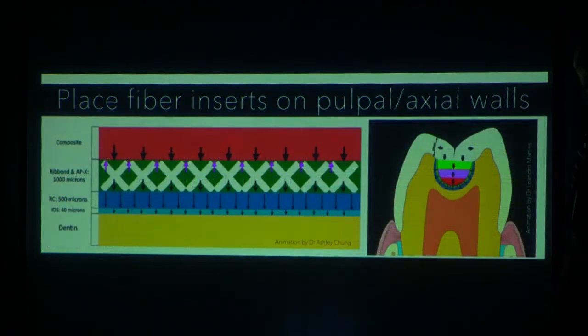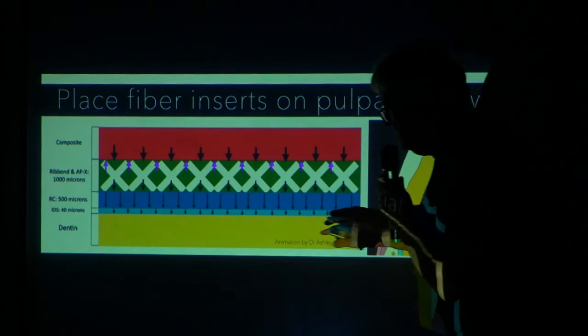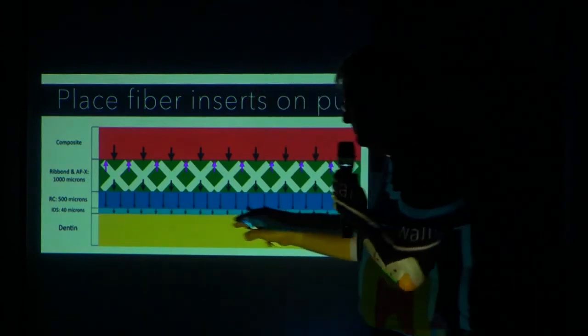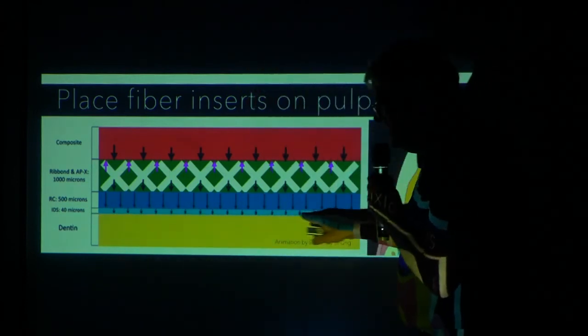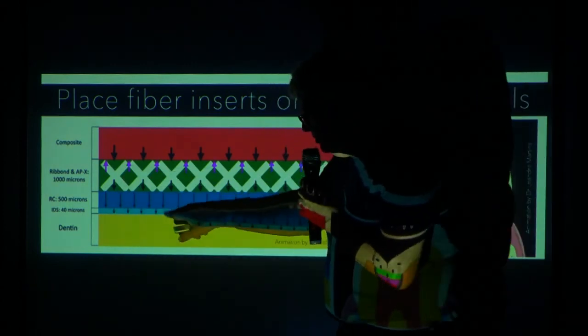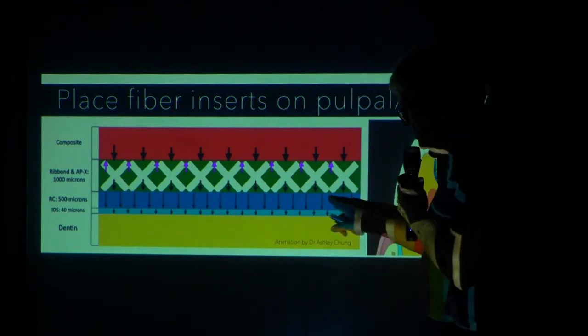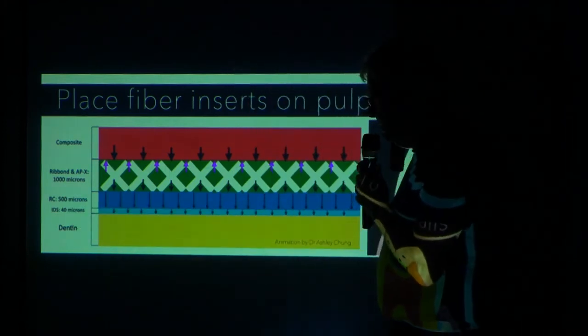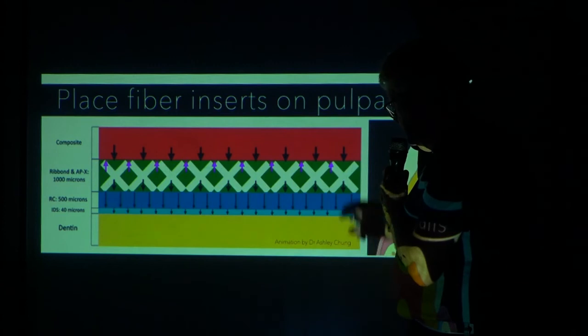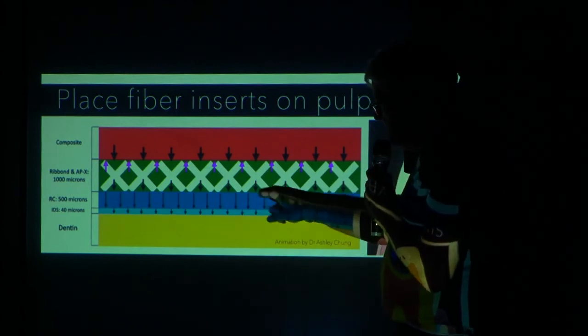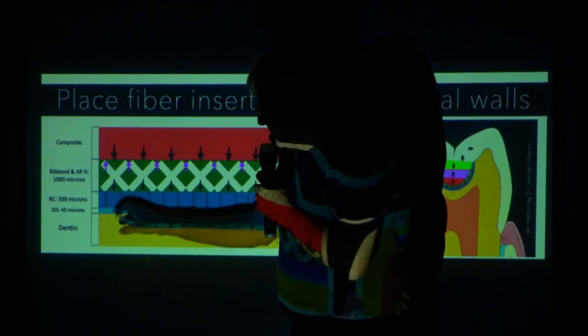So this is how Ribbond works. We have a hybrid layer. This is dentin. Your immediate dentin sealing of 40 microns, once it's polymerized, is moving only towards the dentin, okay? The next layer, this darker blue layer, is your 500 microns of resin coating. You put the light on that, again, it's only moving in one direction because the amount of composite is so small.